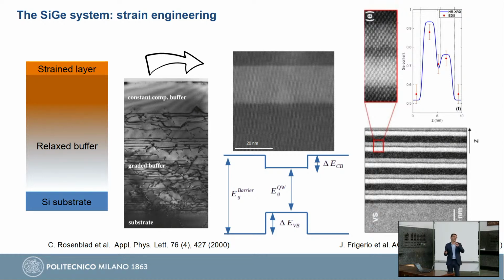The strained layer, we said before, needs to be thin to maintain strain. But then here we have different possibilities. This is a case of a single quantum well. We can grow a 10 nanometer thick quantum well of germanium for electronic or optical application. Or we can also grow a more complicated structure. This is actually the work of Jacopo Frigerio, one of my collaborators. Essentially, these are quantum wells where two asymmetric quantum wells are coupled together by a very thin layer. So you see all these layers repeating here. And for example, here you can introduce an asymmetry in a material which is typically symmetric, like silicon germanium. So for example, you have optical effects that you wouldn't have in the bulk by making this structure.